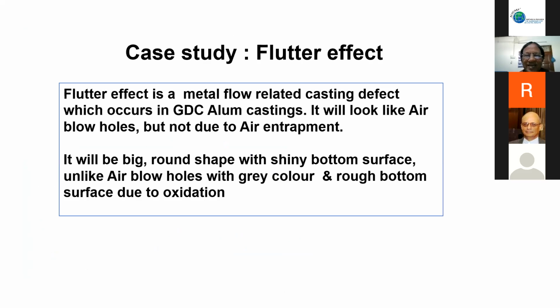This is another case study, the flutter effect. The flutter effect is a very rare defect and less known to many people, because there are a lot of similarities between flutter effect holes and gas holes. Both are circular, but the gas holes are different. Air blow holes are also similar to that. The difference between the air blow hole and the flutter hole is only one area. An air blow hole at the bottom will have some grayish surface due to oxidation. But flutter effect holes have very clean, neat, shiny surfaces. That only can make the difference. Many people won't be able to differentiate between a flutter effect hole and a gas hole.